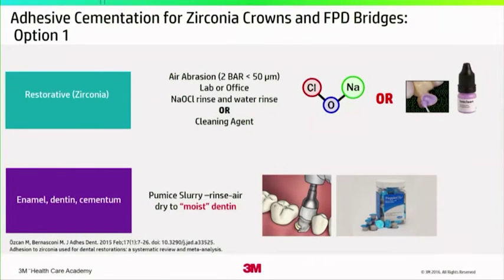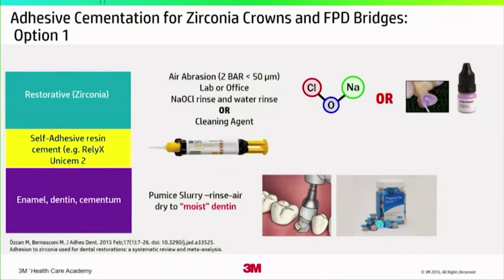Now, if you want to adhesively place zirconia, it doesn't have to be complex either. And the way I've tried to help doctors understand this is that you simply have to provide a clean surface for the zirconia. So the same concept applies here. You would try the restoration in the mouth, do your adjustments. But in a particular case here, we're going to use our sodium hypochlorite or our cleaning agent. We're going to clean the tooth, and we're going to use the self-adhesive resin cement.